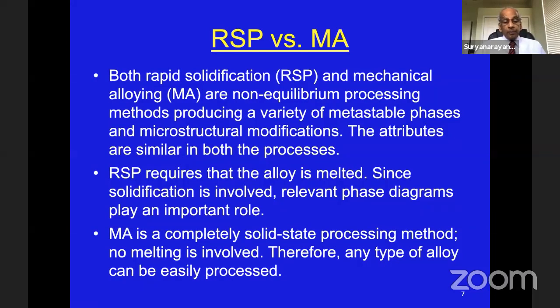But the important difference is RSP, rapid solidification processing, requires that the alloy is melted, because you have to melt it and then solidify it very rapidly. That's why it is called rapid solidification processing. If solidification is involved, that means the phase diagrams will determine what type of phases are produced in these materials. Although metastable phases are produced, which are not part of the phase diagrams, phase diagram still imposes some restrictions on the type of phases that could be produced. On the other hand, mechanical alloying is a completely solid state processing method. That means the phase diagrams do not come into play. And that's the reason why virtually any type of alloy can be processed using the mechanical alloying methods, but there are some restrictions or limitations on how the alloys can be produced by rapid solidification processing methods. So there's an important difference.